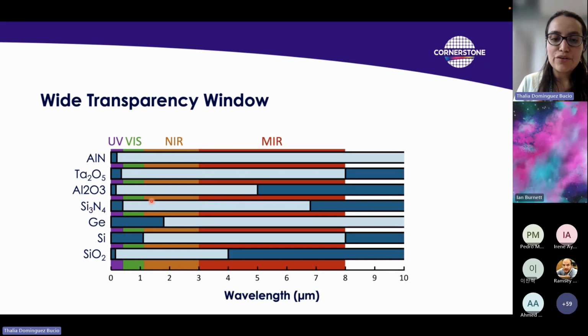Now, this is very important because what it means is that silicon nitride itself can cover a wider range of spectrums compared to the standard silicon photonic platforms like germanium, silicon, and silicon dioxide, because it's transparent all the way from the UV to the mid-infrared spectrum. And although it might not be as good in terms of the transparency window compared to aluminum nitride or tantalum pentoxide, it's one of the preferred materials because it's very standard in the CMOS production line, and there's capability of fabricating at high volumes.